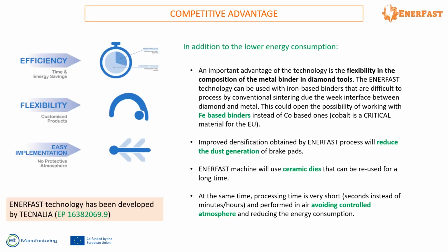Other possible advantages of the technology. One is efficiency; we were talking about the energy consumption. The other one is flexibility. Why? Because in a conventional powder metallurgical process, you fill the die or the furnace with all the materials the same, because you need to set a cycle, and the cycle should be the same for all of them. In this case, you can change the process very quickly. You can change the conditions, you can even change the composition you need to produce, and it's much more flexible than a conventional furnace. And also it's easy to implement. As you see, it's a simple machine similar to a cold press, but of course a special one.